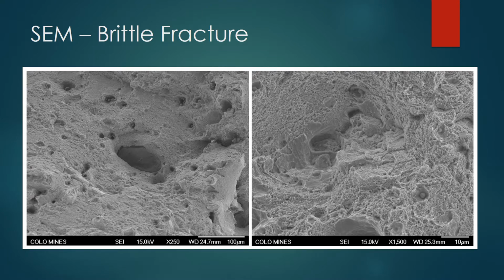Here is the additive manufactured sample, where we do see brittle fracture. In the image on the right, we see some step downs and what looks like cleavage where the two different boundaries meet each other. And when you have these smooth-walled cavitations or cavities in the object or the specimen, as you stretch it, the planes start to shift relative to the direction of the stress and induces brittle fracture.